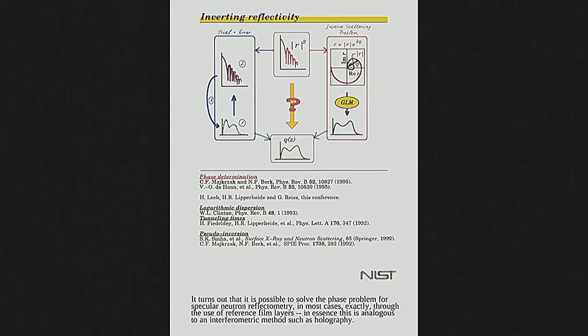We do not measure the amplitude and the phase, we measure this quantity squared. So all of the phase information, all of the location of where things are in space that are determined by the phase of the wave, the neutron ruler, if you will, as it goes into the material, that's just lost. We just squared it away because we only know how to measure the squared wave function. Because it's the square of the wave function that's the probability of finding the scattered neutron or X-ray at some point in our detector. That's all that quantum mechanics allows us to measure.